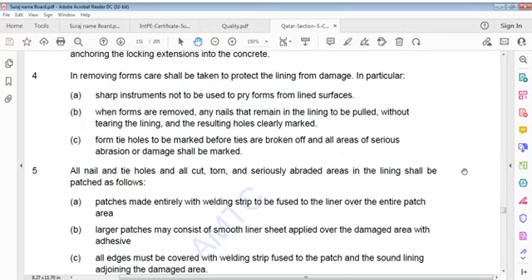In removing forms, care shall be taken to protect lining from damage. In particular, sharp instruments not to be used to pry forms from lined surface. When forms are removed, nails that remain in lining to be pulled without tearing lining and resulting holes clearly marked. Form tie holes to be marked before ties are broken off, and all areas of serious abrasion or damage